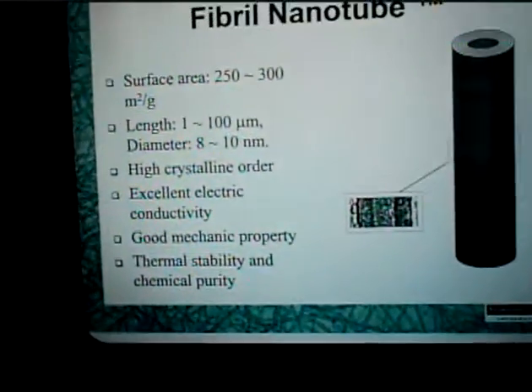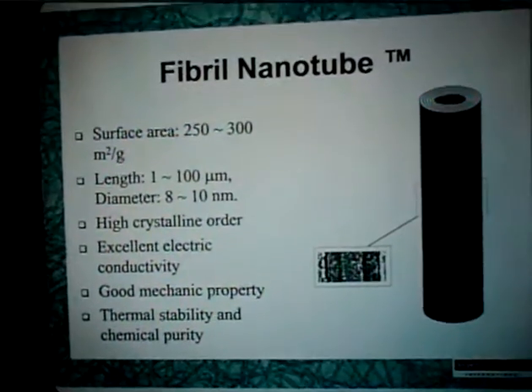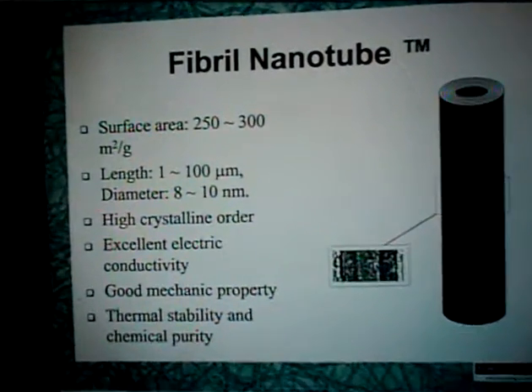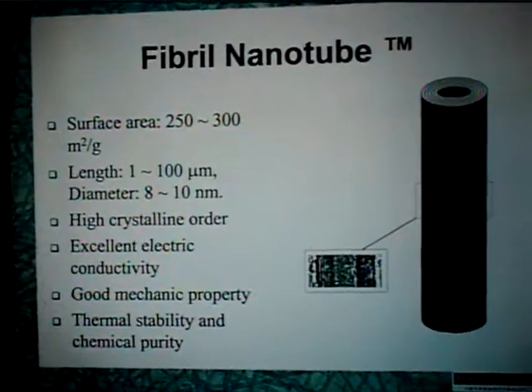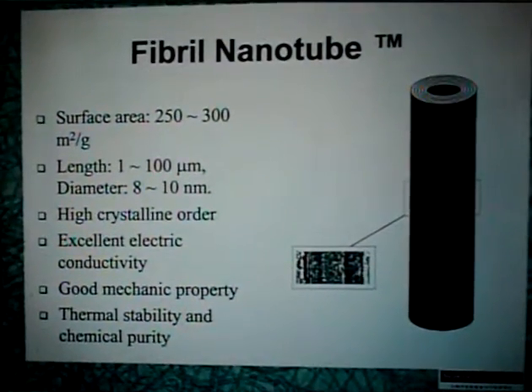Surface area is quite adequate, between 250 and 300 square meters per gram. Very pure carbon, high crystalline order, excellent electric conductivity. I think most of the sales now for those materials are for adding into polymers to make plastic. They become conductors. The mechanical properties are also very good. They can make extrudates of those things. So it's not a very fine powder that will stay in a reactor. They can make a pellet just like you can make with an oxide. Of course, very high thermal stability and chemical purity.